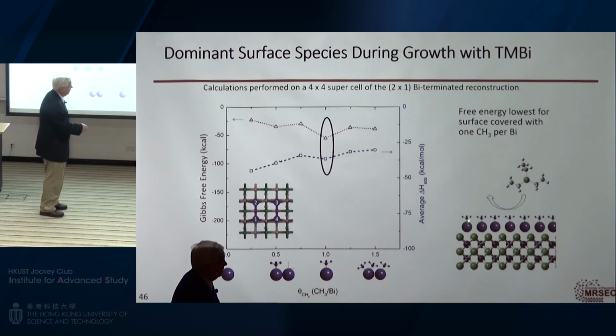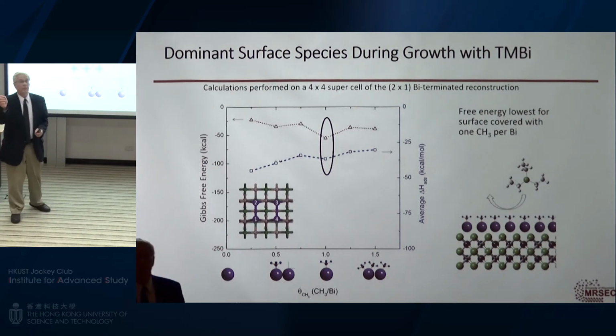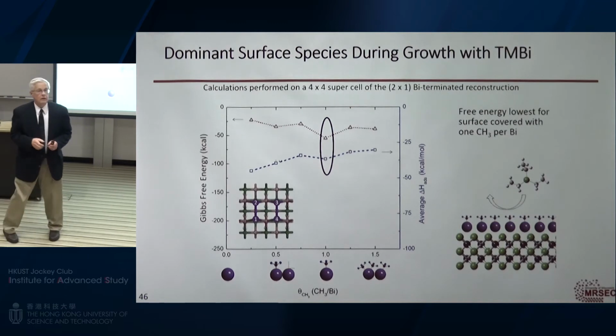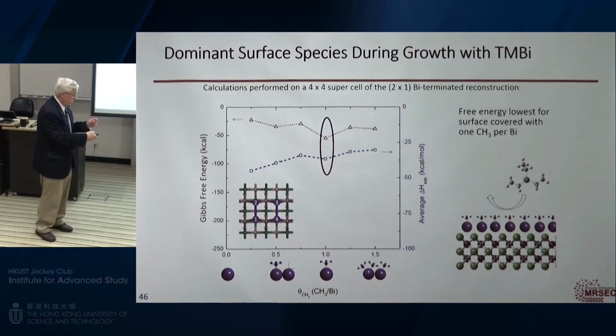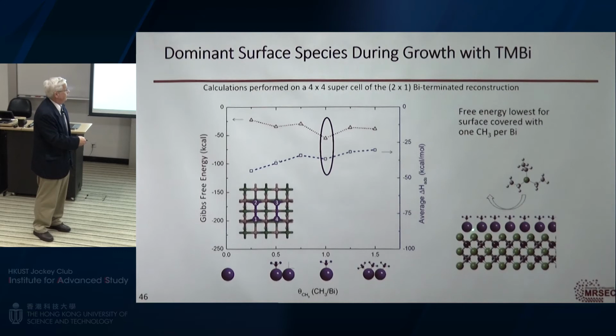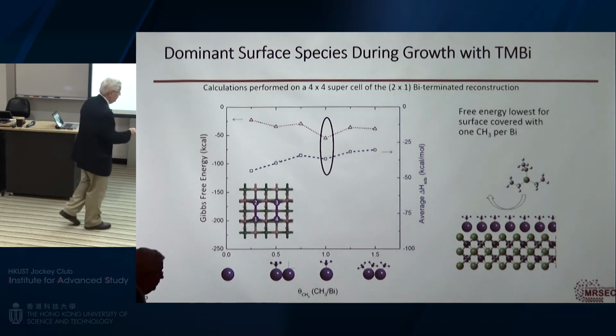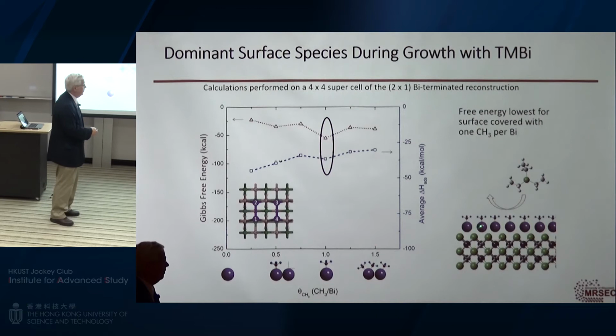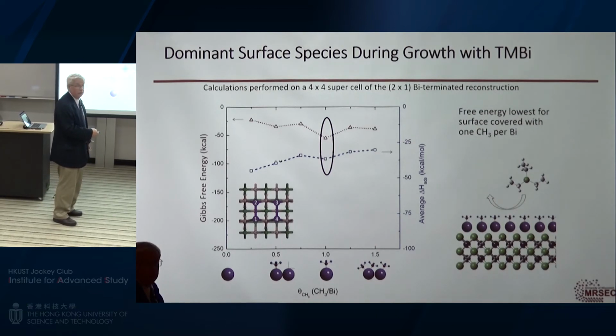But the other thing that it did is that having these methyl groups on the surface kept atoms from diffusing around. They did that because they took up surface sites. For an atom to move, it has to go from one site to another, to another, to another. With these methyl groups in here, sterically, it prevented those sites from being open for diffusion. So the bismuth atoms that came down stayed there because they were blocked from moving around.